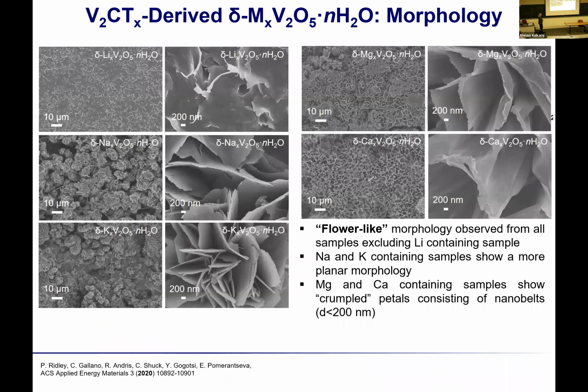But what's most interesting, I tried to emphasize on my previous slides that in the case of alpha V2O5 precursors, the morphology of all the products was one-dimensional. We synthesized nanobelts. Here, the morphology of MXene-derived bilayered vanadium oxide is drastically different. We see two-dimensional plates.